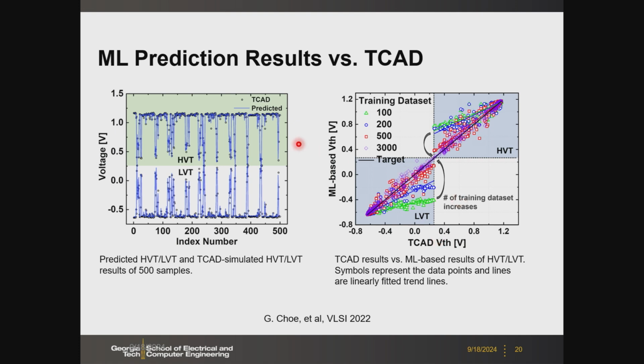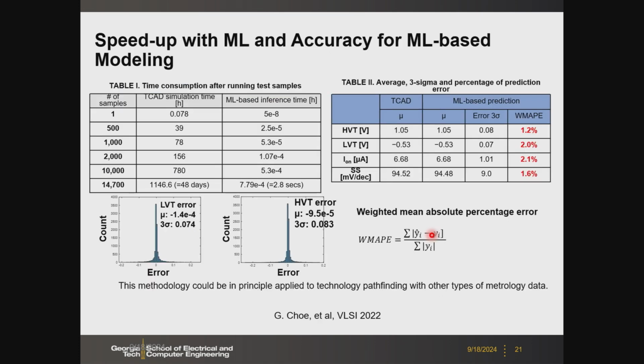So here I show a calibration first: machine learning predicted results in terms of the threshold voltage versus the TCAD across 500 samples. And also here, depending on the number of data sets, for example if we have 3,000 points as the training data set, then we can have pretty good fitting between the machine learning predicted VTH versus the TCAD VTH. So later when we do the inference, we can just get the results in seconds in terms of the sigma of the threshold voltage, on-state current, subthreshold slope, and so on, given the polarization map of your thin film, right?